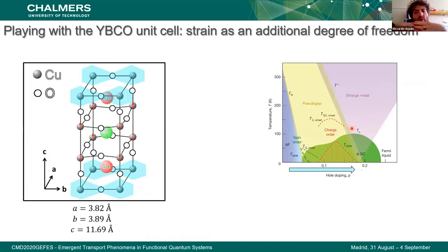And now to investigate deeper into charge order, what we do is we want to study the material in thin film form. Thin films are in fact crucial because the strain induced by the substrate can be used as an additional degree of freedom. And in this way, we play with the unit cell, since we can, in this way, achieve something which is sort of a new material. And in the case of YBCO, this is the unit cell, as you also saw in the previous talk. The cell is orthorhombic since copper oxide chains are unidirectional, going along the b axis direction. And basically, doping the material means adding oxygen atoms into the chains that then dope with holes the copper oxide planes, giving rise to all the phenomenology that we can observe in the phase diagram.